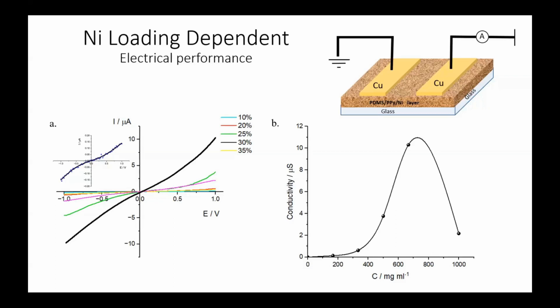We have an IV effect, which is a more high performance. As you see here, when we have around 30 to 35% by weight, we have a good electrical performance of the latex. When we add high amounts of nickel, we can see degradation at some point after 800 milligram per milliliter.